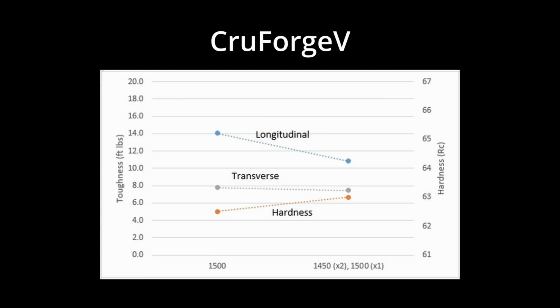I think that is likely due to two factors. One, the chromium addition in CruForgeV does change things, just like we were talking about with 52100 earlier. So its carbides dissolve more slowly, and it is not as sensitive to overheating and getting excess carbon in solution. And number two, we used a lower temperature for the first two quenches, so maybe that was not as detrimental as doing everything at 1475.